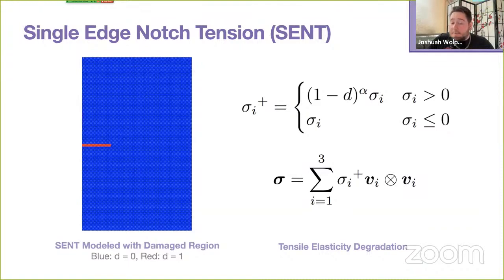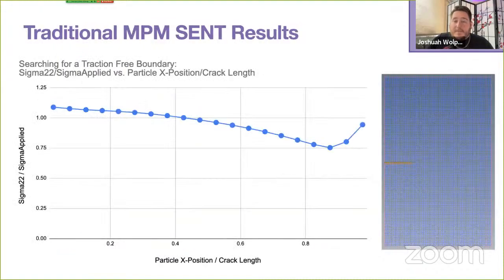So let's take a look at how MPM performs on this simple validation test. Here we're looking at the particles along the top edge of the crack, and we plot the stress concentration factor, sigma 22 over sigma applied, against the proportional distance from the crack opening the particle is. So each data point is the stress concentration factor at a particle along the top edge going from left to right. And by now you've probably noticed that this stress concentration factor is quite far from the zero that we want to see here along the crack surface. So what's going on here, and how could MPM produce all these beautiful animations but be so directly struggling with modeling a traction-free crack surface?